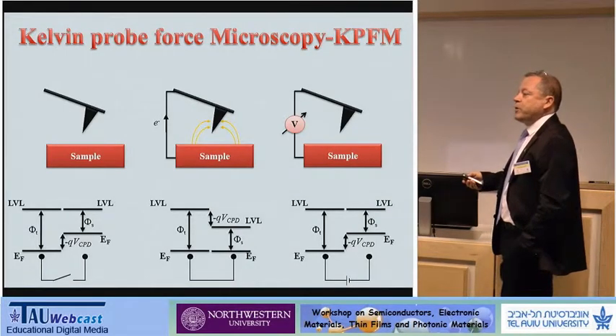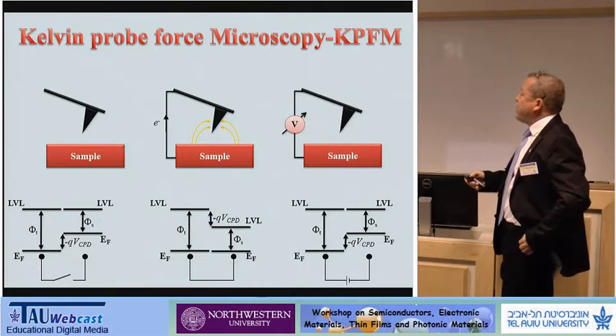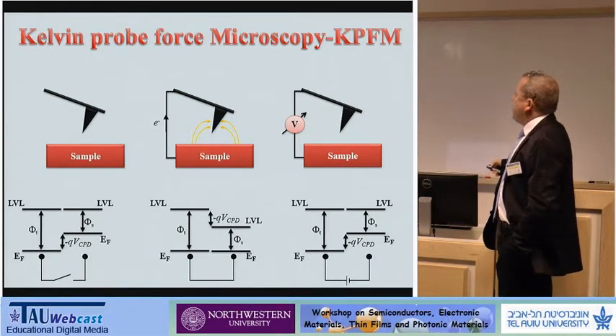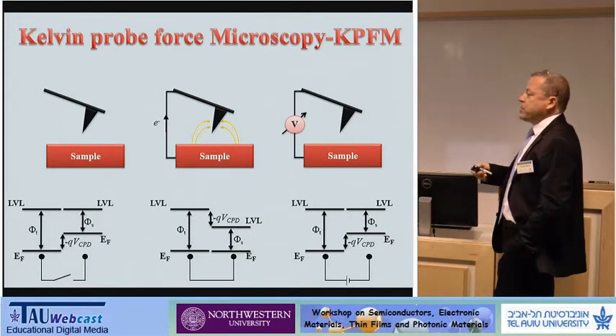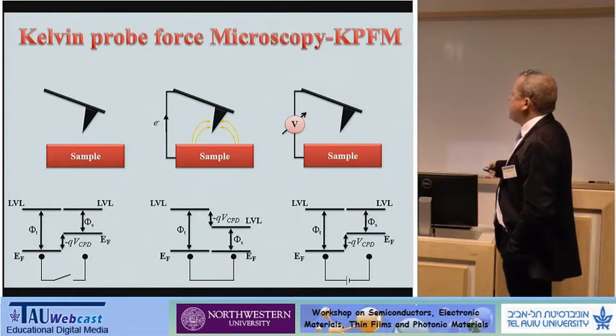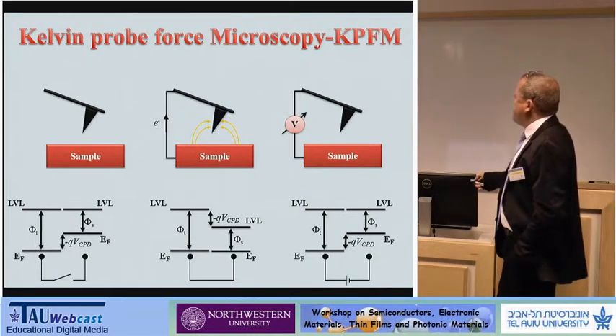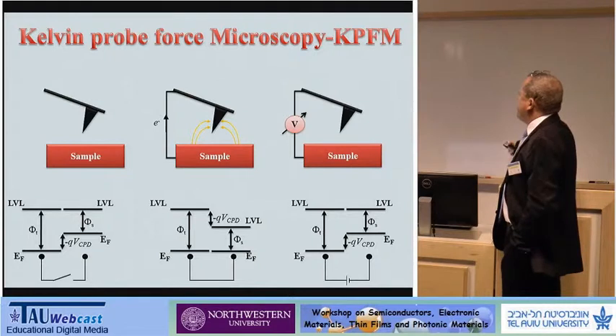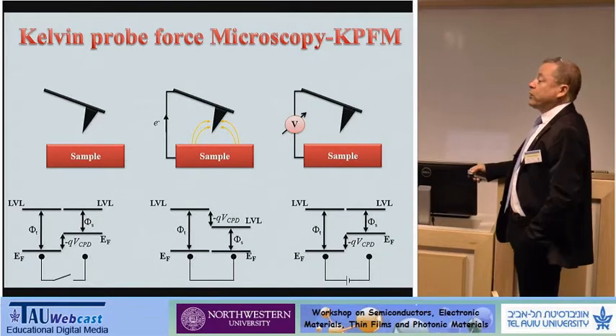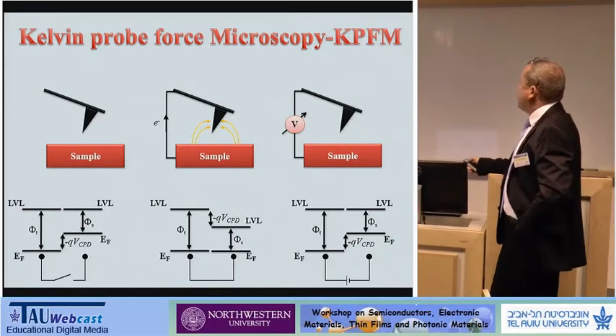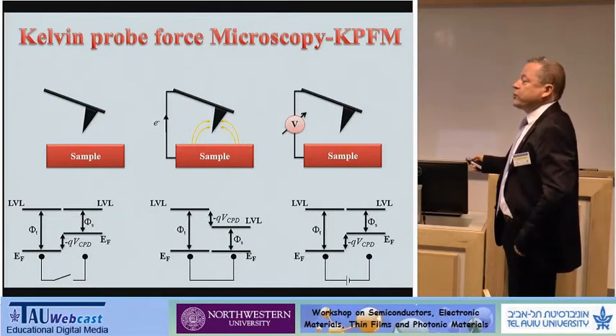The principle of Kelvin probe force microscopy is based on the macroscopic Kelvin probe. You basically have a tip and a sample. When you connect them, you equalize the Fermi level. This forms a built-in potential between the tip and the sample. It's like a capacitor. This potential equals the contact potential difference, or as we mark it, VCPD. And by a feedback voltage, you equalize the local vacuum level or discharge this capacitor. And by the feedback voltage needed to do this, you can measure the contact potential difference or the work function. If the work function of the tip is known, you can measure the work function of the sample.